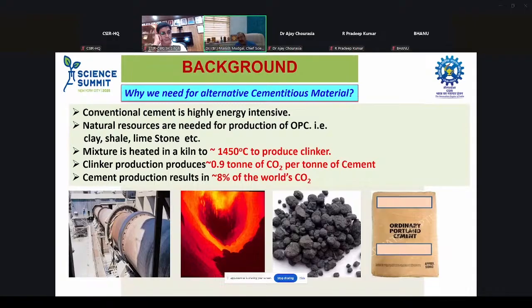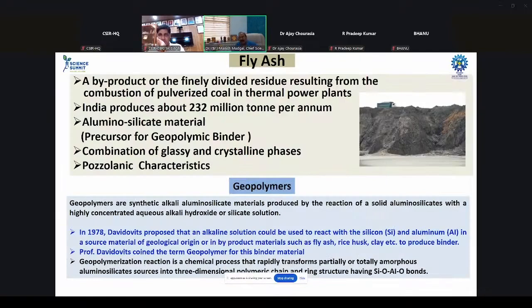This is the background: cement production produces around 0.9 tons of CO2 per ton of cement. It is a highly energy intensive process. Around 1450 degrees centigrade is required to make the clinkers, and cement production results in 8% of world CO2. So this is a high embodied energy material, as well as a highly polluting process. So we have developed this geopolymer utilizing fly ash.